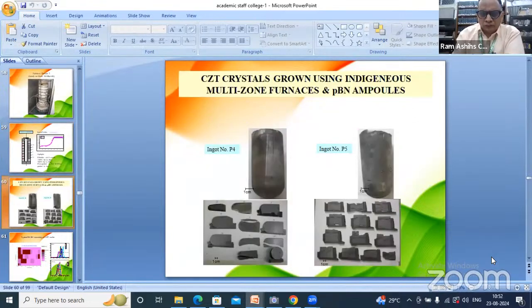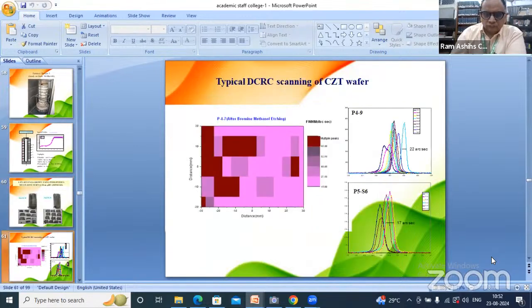This is the output of the crystal grown in this furnace. You can clearly see the twin line, and different grains are also visible in the P5 ingot, and the twin line is clear in the ingot P4. And the large area grain wafer is shown in the figure. This is the DCRC, scanning double crystal rocking curve. This shows splitting at the edges and perfect crystalline quality in the middle of the crystal.